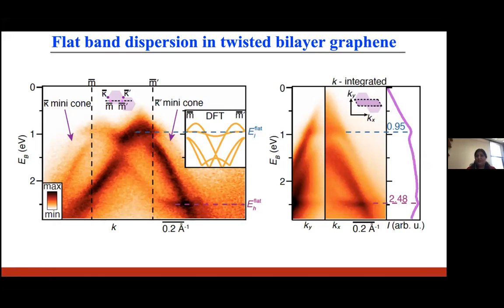We observe two flat bands, and this flat band at a higher binding energy comes from the bottom graphene Dirac cone, where it crosses the branch of the top Dirac cone, and it is attributed to the dispersion around the endpoint of the mini Brillouin zone, where the Van Hove singularity of the isolated graphene occurs.